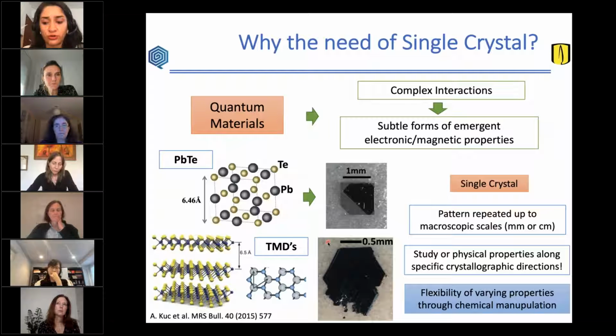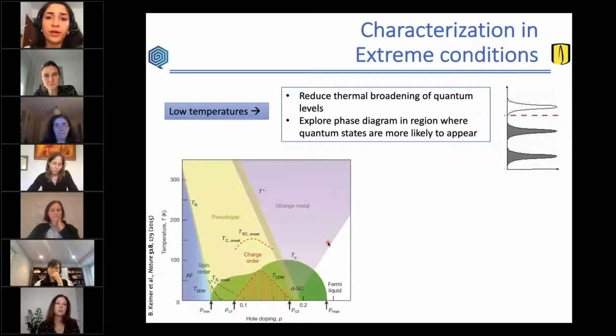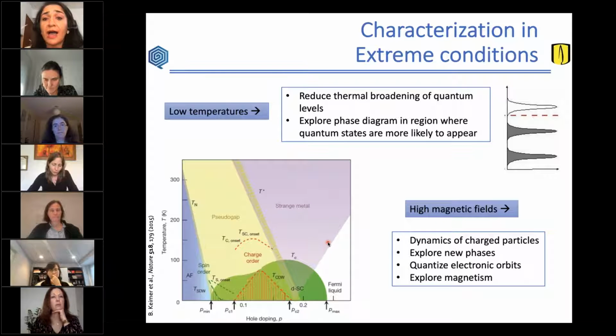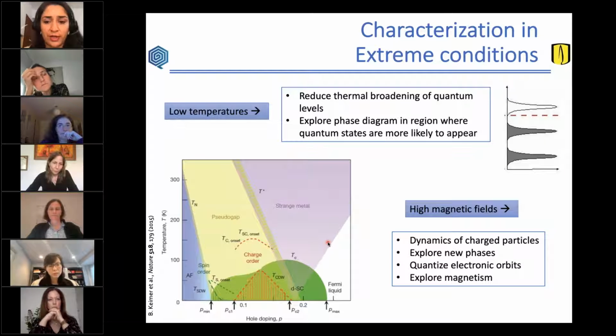All right, and we also use extreme conditions in order to characterize these electronic phases in these ground states. So we use low temperatures to reduce the thermal broadening of these electronic states and be able to resolve in full glory their behavior. And we use high magnetic fields to reveal particularly the dynamics of charged particles, which is different and is characteristic of different electronic ground states. So I'm going to show you now some examples of some recent experiments and work we have done using this philosophy that we handle in our group.